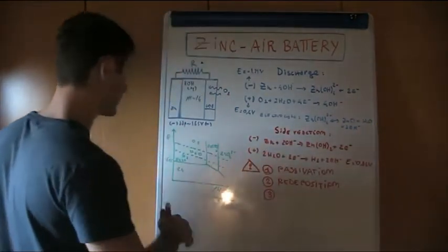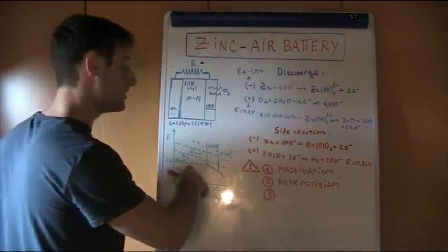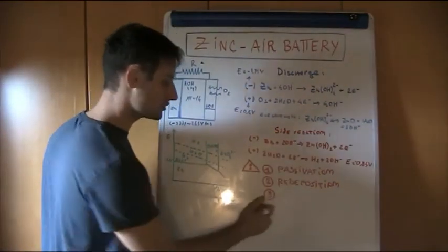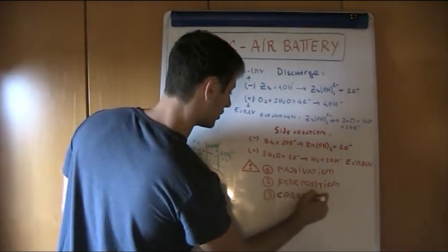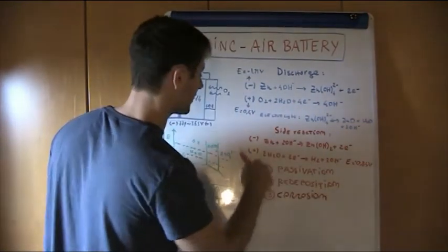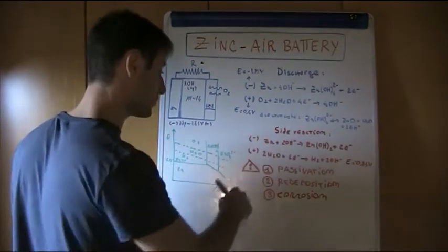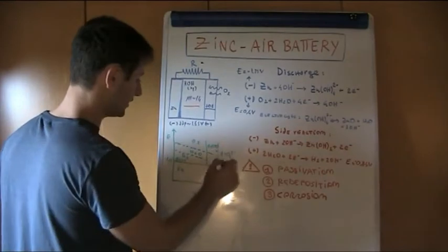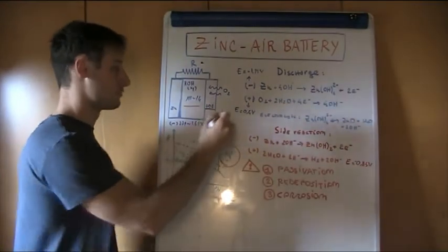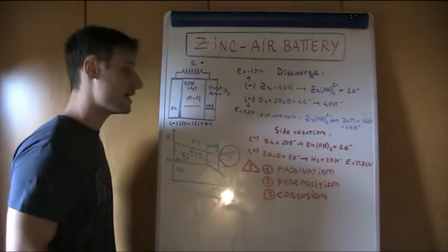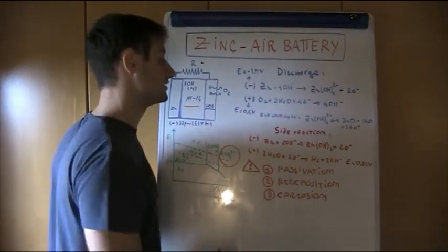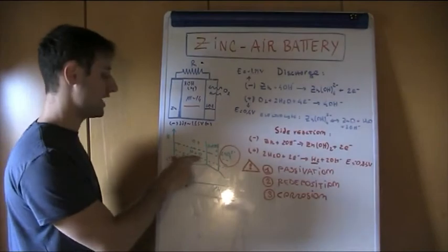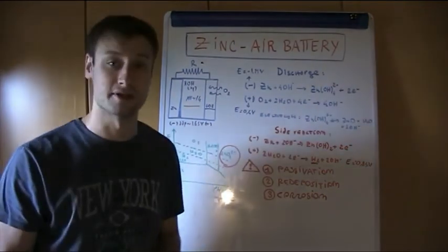And we have described, according to the Pourbaix diagram, basically the possibility of side reactions, and so the corrosion of the electrode, losing zinc, promoting the evolution of hydrogen. But we have described how, working in superalkaline conditions, we are promoting the formation of zincate, and so synthetically fighting the generation of hydrogen, even if from a theoretical point of view it is promoted in thermodynamics.